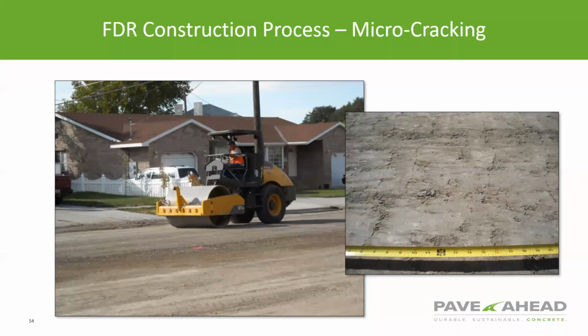There's something that Don said that triggered it. We're doing a project, actually a demonstration project up in Fargo, North Dakota, and we did about half a mile of road for them with all these different cross sections. I'm walking it with the engineer a couple of weeks after, and we see just normal cracking, like every 100 feet, a hairline crack or something like that. Then all of a sudden the cracks got like 15, 20 feet apart. He's like, "What's going on here?"